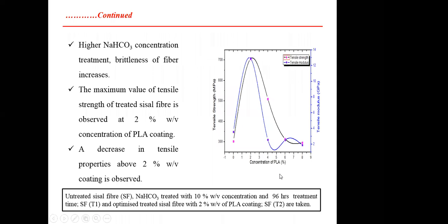After treatment, we have done the coating on the fiber. At 2% coating, a higher value of tensile strength is obtained, and thereafter the values decrease. Because of the treatment, some hemicellulose is removed from the surface of the fiber, due to which properties get declined.